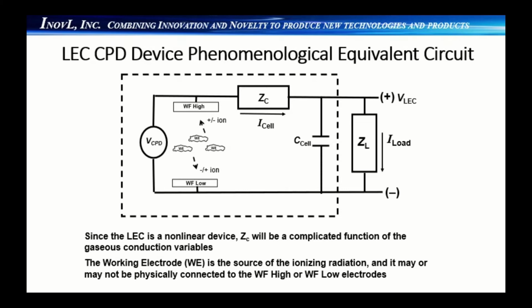By now, if I was there in person, people would probably be pointing out an error on the slide, since it implies that both plus and minus ions may go to each electrode. We all know that positive ions are assumed to be attracted to the low work function electrode, and negative ions will migrate to the high work function electrode. However, multiple parameters of LEC cell design are involved, leading to the situation where positive ions will actually migrate to the high work function electrode and negative ions migrate toward the low work function electrode. These results are predicted by theory and have been experimentally observed.